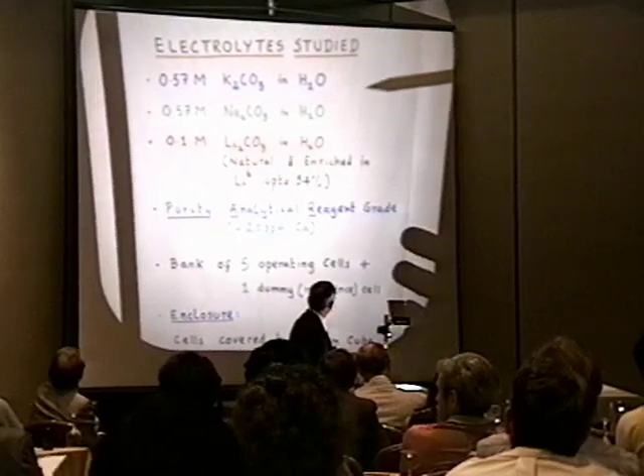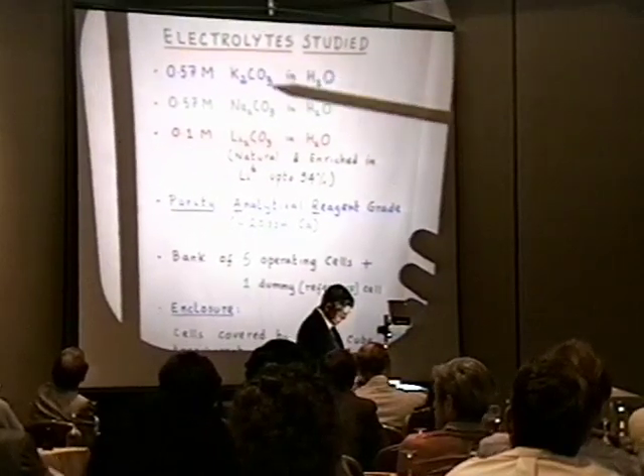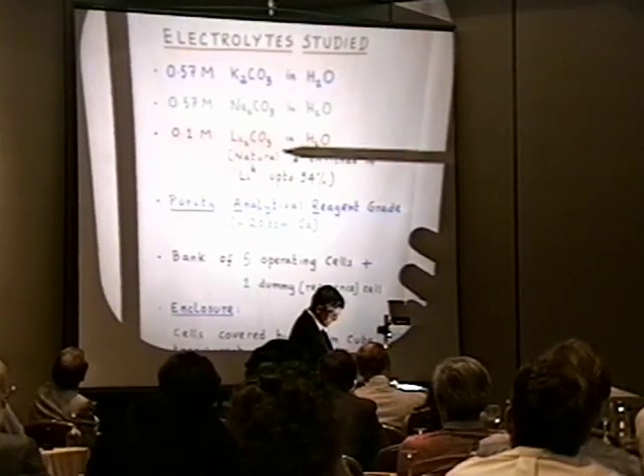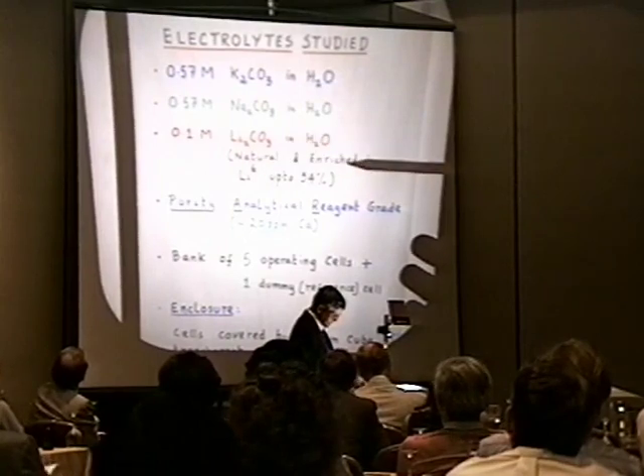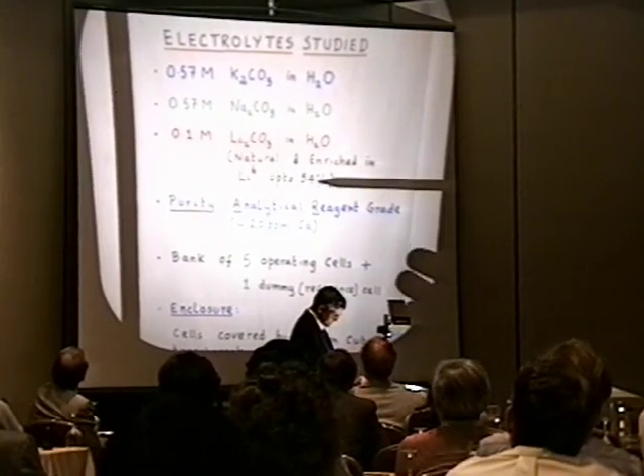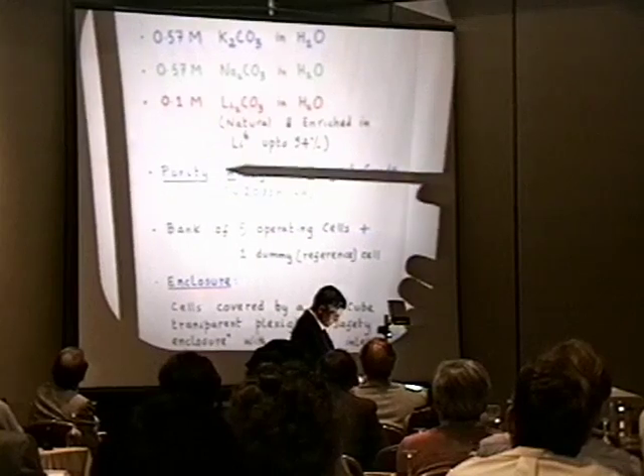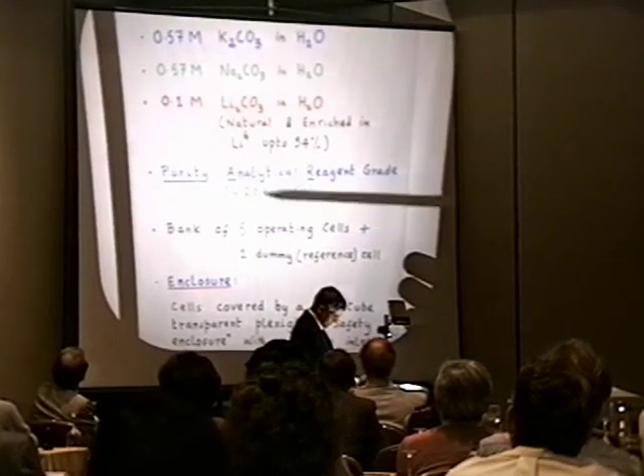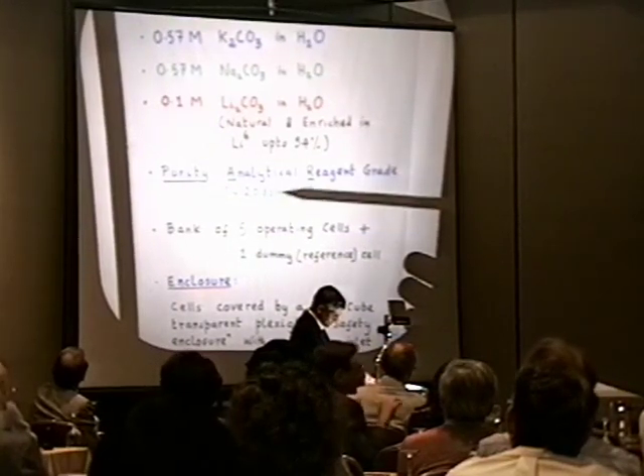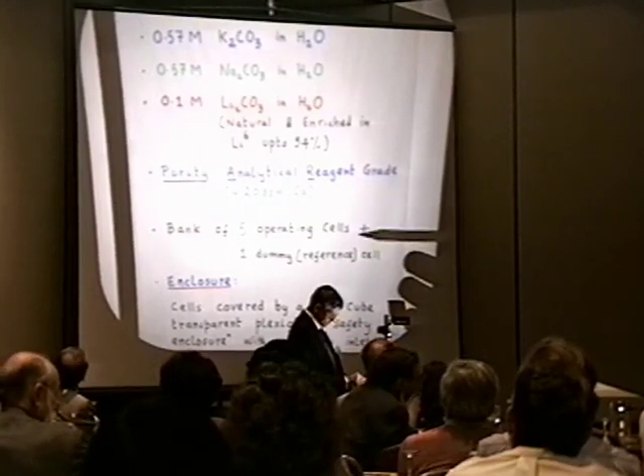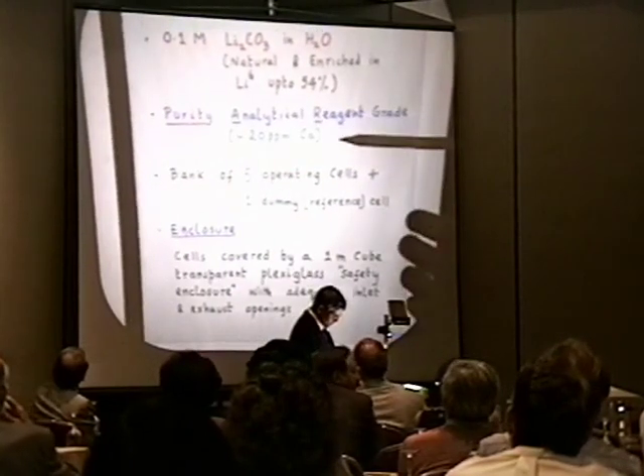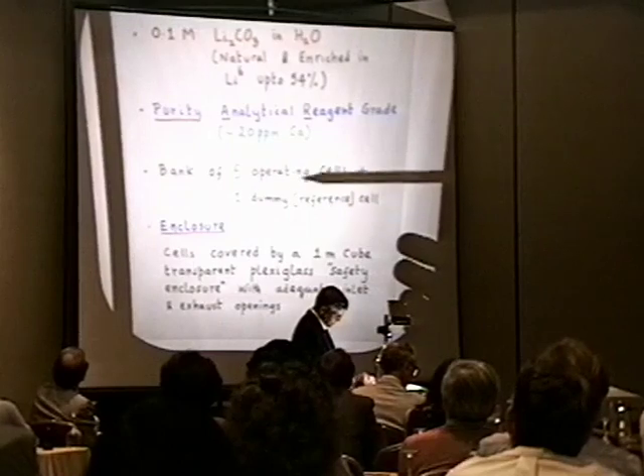The electrolytes studied were potassium carbonate, sodium carbonate, lithium carbonate, both natural and enriched. Lithium 6 enriched to 54%. The purity of the materials used are analytical reagent grade. Usually they contain about 20 ppm of calcium, and that's important for you to note. I'll come back to that later.